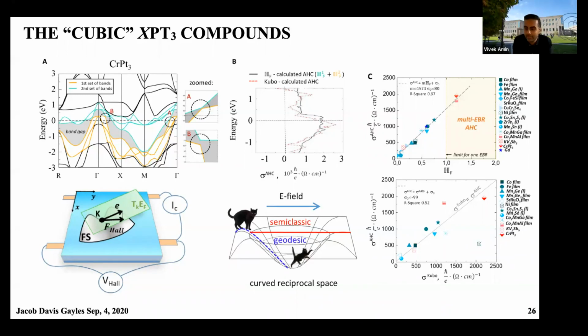So is it kind of more of an efficient way of essentially? It's very efficient. Because also we don't have to use any interpolated band structures. So we can just take the pure self-consistent calculation and measure that out. There's still some things we need to work through, but it's quite efficient in the sense. So I think we converge things already at like 30 K points per direction.